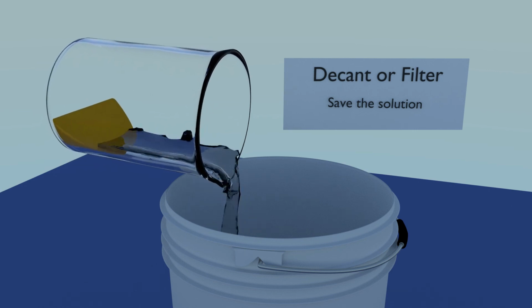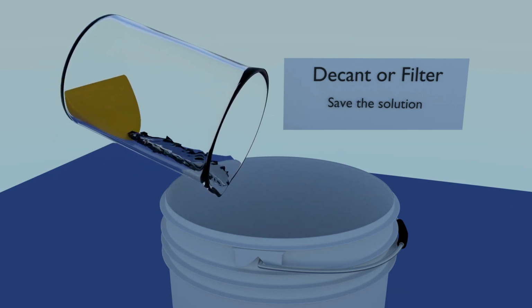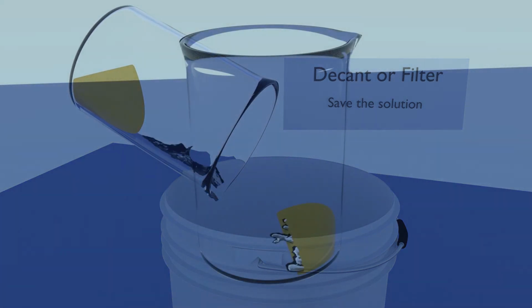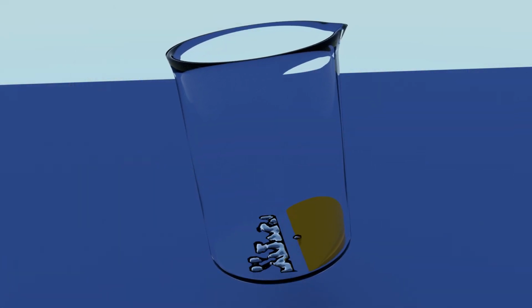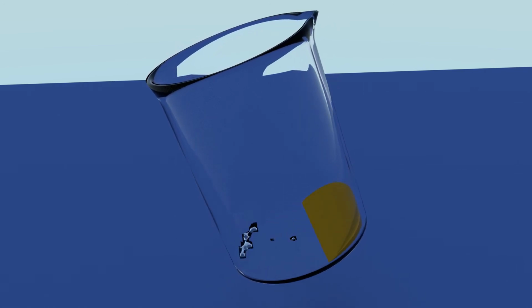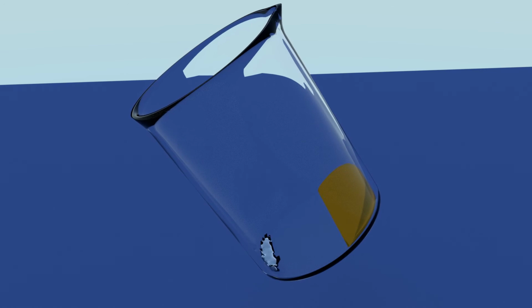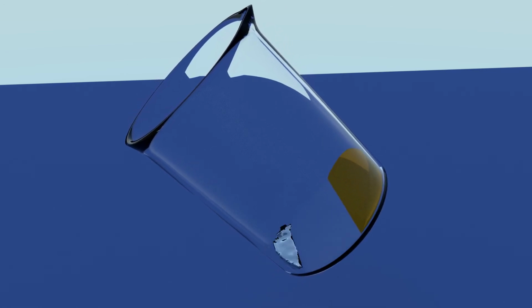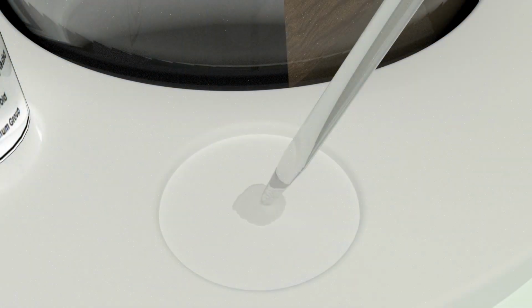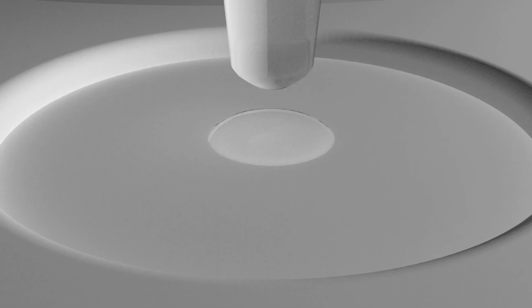2 rinses is usually enough, but we'll test to make sure. A small amount of water will cling to your gold mud. We'll take a few drops of that water and test it for impurities. Tilt your beaker. Water will drip off the mud and then puddle in the corner of the beaker. Take a sample from the puddled water and place it on a spot plate, mirror, or paper towel. To test, add a drop of ammonia test liquid. If you see any color change, even the palest shade of blue or purple, rinse again, and then test again.